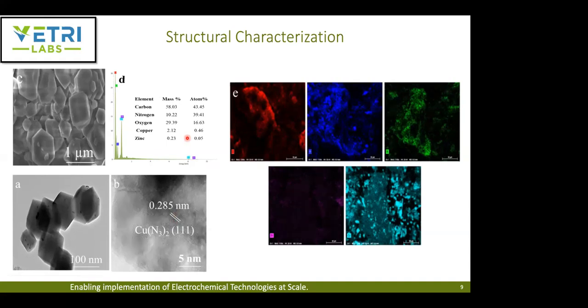And also with this elemental mapping, they can see a uniform dispersion of different elements, confirming the presence of copper in their finally obtained structure. And also in the TEM, you can further see that the composite metal nanoparticles are coated in the carbon layer or at the top of the carbon.